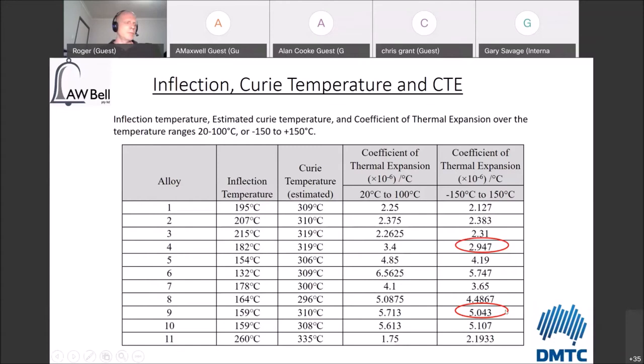Now, when you say, well, why is that important? Well, basically, when you have something which has got sensors in it, you need to have windows for the sensors to look out of and go through. So quite often there's a requirement that your window and your material holding the window actually has to have the same coefficient of thermal expansion. So what this tended to suggest to us was that, well, if we didn't need the absolute minimum, we could actually tailor the coefficient of thermal expansion to match the window material quite well if need be. So that was also an interesting outcome.